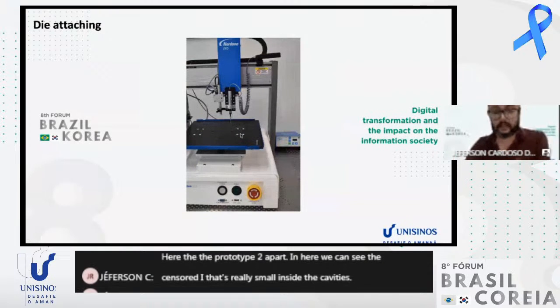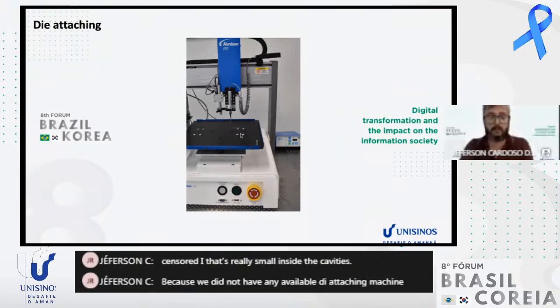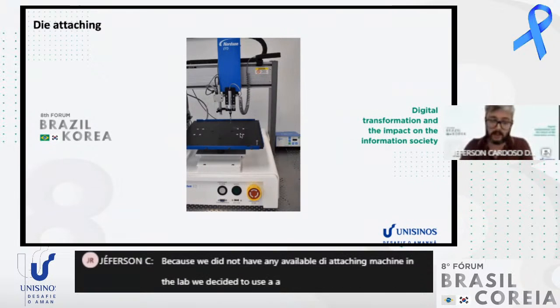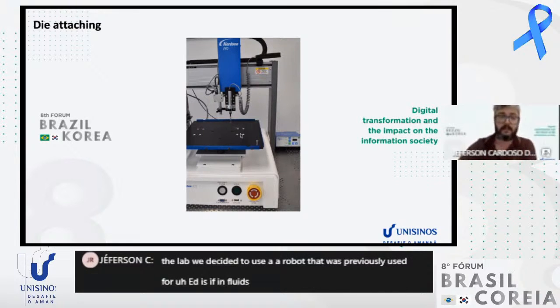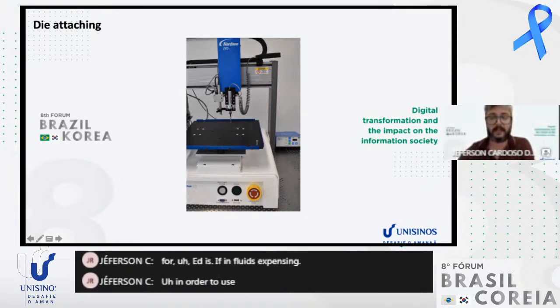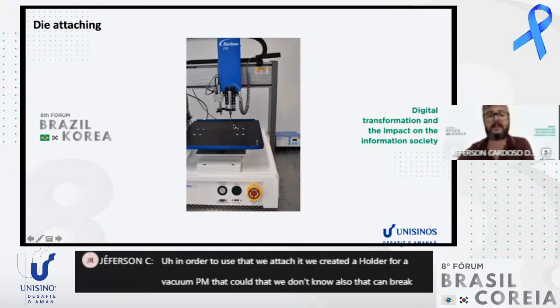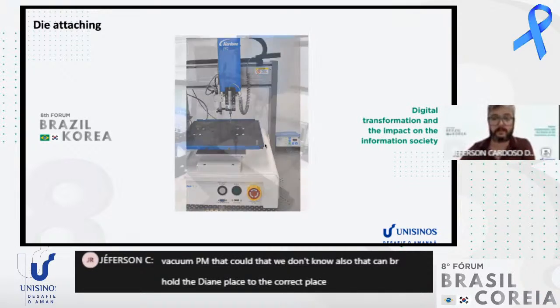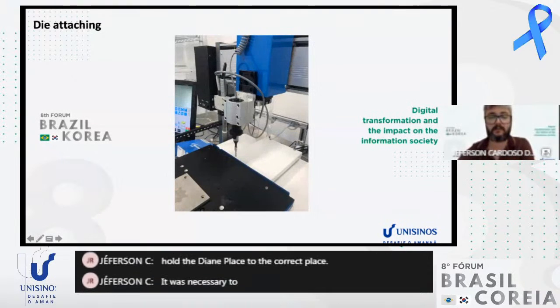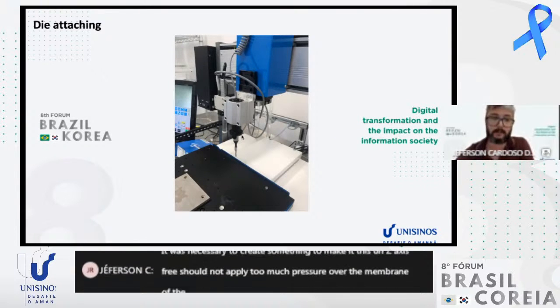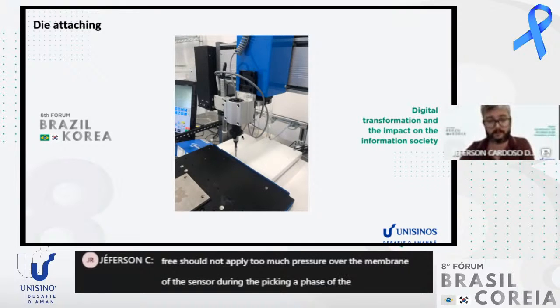Because we did not have any available die attaching machine in the lab, we decided to use a robot that was previously used for adhesive and fluids dispensing. In order to use that, we created a holder for a vacuum pen with a nozzle that can hold the die and place it in the correct place. It was necessary to make the Z-axis free, to not apply too much pressure over the membrane of the sensor during the picking phase of this production step.